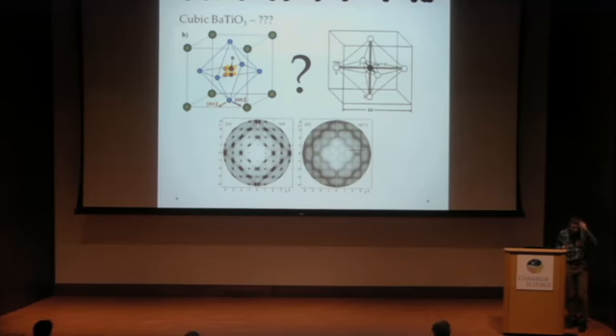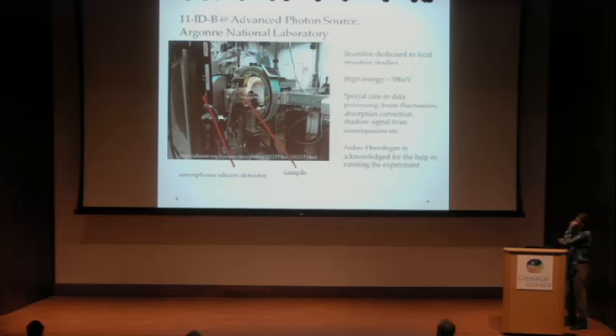So the question is, what happens in the cubic phase? So this was tetragonal. And is it somehow something special related to these diffuse scattering lines? Because for a long time, there was debate: if we have these diffuse scattering lines, are they related just to the soft modes, or is there something with longer-time dynamics or even static disorder which exists in the material? And okay, so that's our experiment.